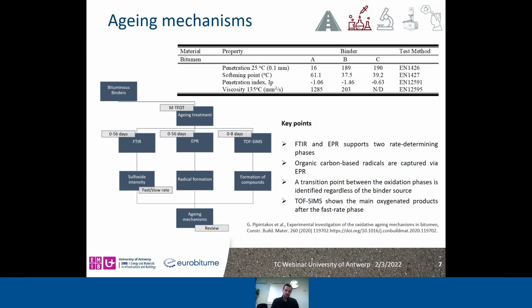The key points, which I will also present more clearly in the next slides, support that indeed we have two rate-determining phases. It was also the first time that we were able to capture, for bitumen oxidation, organic carbon-centered radicals with an advanced spectroscopic technique called electron paramagnetic resonance. And for all the binders, we saw a clear transition between the two phases, the slow and the rate-determining phases. And finally, time-of-flight secondary ion mass spectrometry, or in short TOF-SIMS, was used in order to find more details about the oxygenated products after this transition point, which was found for all these three binders at around 8 days.